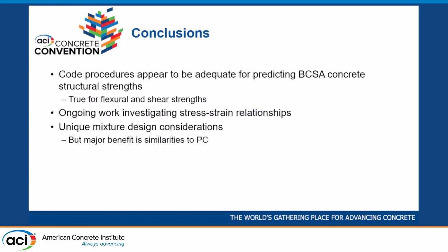In conclusion, from the testing we've done so far in terms of flexural and shear strength, the code equations appear to be adequate for BCSA cement. We're getting similar results as we'd expect for Portland cement. We have that ongoing work looking at stress strain for BCSA cement concrete. Also Betty talked about her work looking at repairs with BCSA cement, and I talked about some of the unique mix design considerations. I actually think that's a strength of BCSA cement compared to some other alternative cement technologies. It's sort of like Portland cement: you can buy it in a bag, you mix it with water, it makes concrete. So it's a little bit simpler than some other alternative cements.